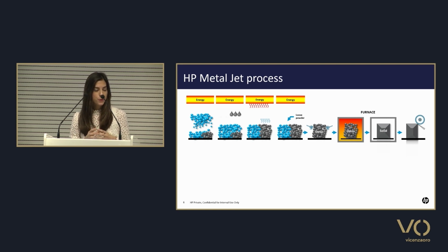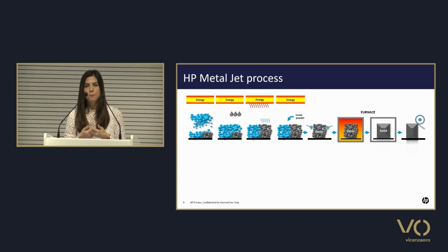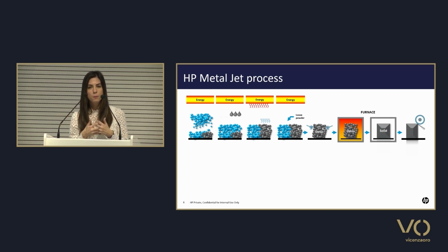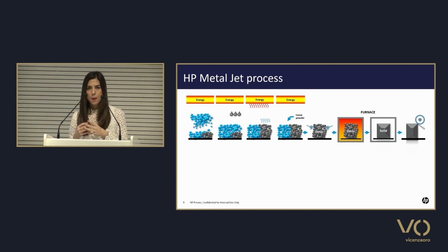Once you finish the printing process, layer by layer with the print heads putting the ink, you need to apply even more energy, because this ink is basically a polymer, and you need to cure the polymer to make sure the polymer chain is really activated and you are activating the glue mechanism of the polymer chain. You apply this energy, which we call the curing process. And finally, what you have is a box filled with powder that has not been printed and parts that have been printed. We call these parts green parts.